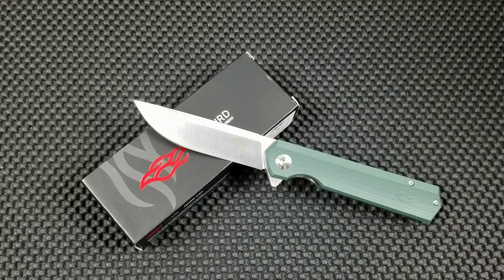You're looking at 1.5 to 1.6% carbon content, 11.5 to 12% chromium content, and it is vanadium alloyed at 0.9 to 1.1% vanadium. As far as Rockwell hardness, you can expect D2 to come from most manufacturers in the 60 to 62 Rockwell range. And what you're going to get out of this steel as far as edge retention and wear resistance, good to very good edge retention.